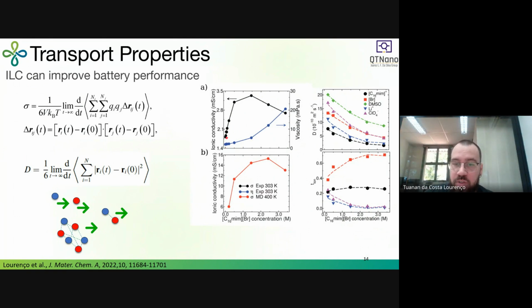However, in the ionic conductivity, there is an increase, then we reach a maximum value and there is a decrease. So this behavior here in the first half was not expected. So how can we understand it? To understand this behavior and go deeper in its characterization, we ran classical MD simulations.